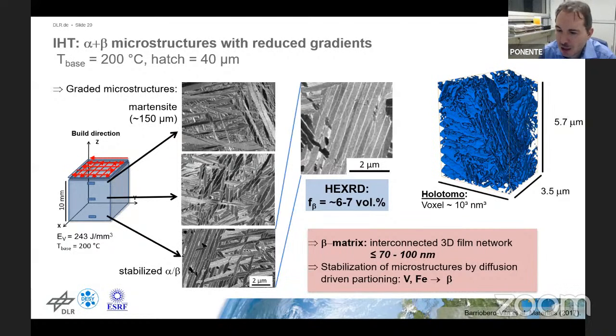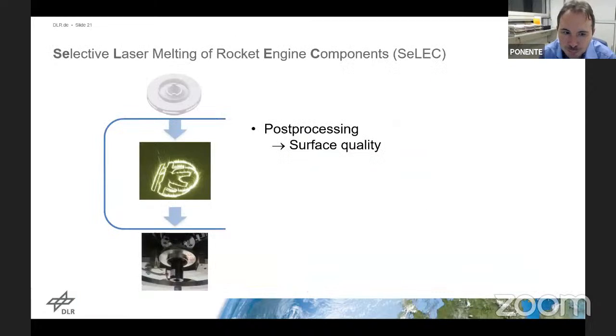And this beta phase, actually, I should have mentioned it in the beginning, is very important for us because it's the phase that will allow the best ductility, or it will be the phase that will be easiest deformed in the material. The alpha or alpha prime are rather high modulus phases that are not accountable for the ductility in the material in the end.